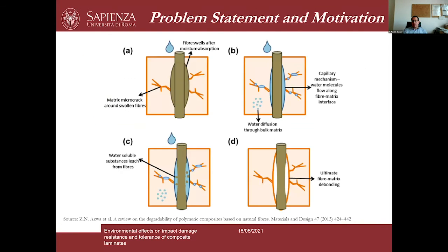And as Luigi mentioned in his presentation, there is also a very strong effect of moisture on natural fibers. And this is something that is not observed with conventional fibers. So carbon fibers, glass fibers, that do not tend to absorb water. But this is not true for natural fibers. Natural fibers are mostly hydrophilic. And what happens with natural fibers is that they tend to absorb a large amount of water. And when they absorb water, they tend to undergo swelling. And what happens is that this swelling creates matrix microcracks around the swollen fiber, and these microcracks can actually make capillary actions much easier. And so we have much water which is actually attracted to the fiber itself.